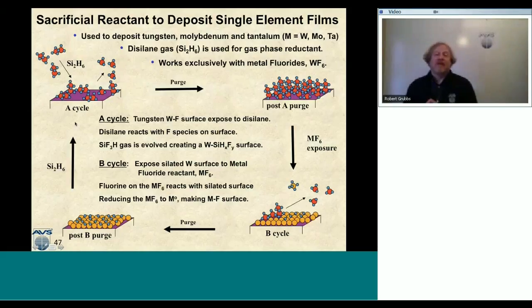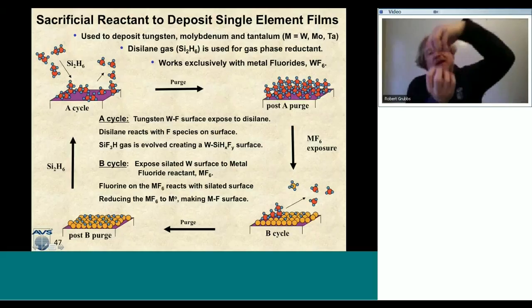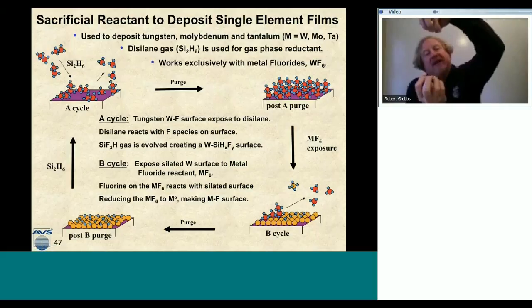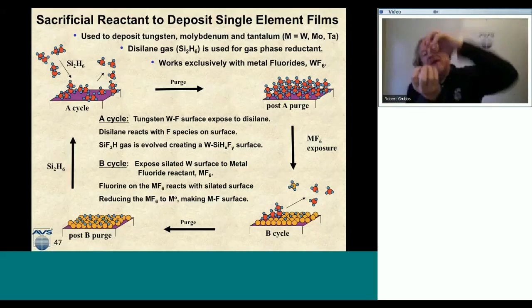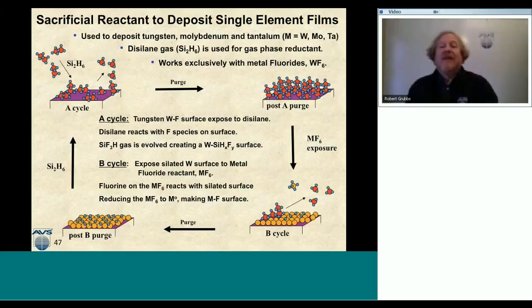Now, the single thing to point out about this chemistry is that the layer thickness of this disilane surface is going to determine the growth per cycle of how much of this tungsten goes down. So at certain temperatures, at higher temperatures, we can get silicon-silicon bond insertion and actually grow a multi-layer of this fluorosilated species on the surface. And so if I have a thick fluorosilated species, then I come in with my metal hexafluoride, I will put down more tungsten metal onto the surface. So the surface growth per cycle is controlled by how much of this fluorosilated species is on the surface.